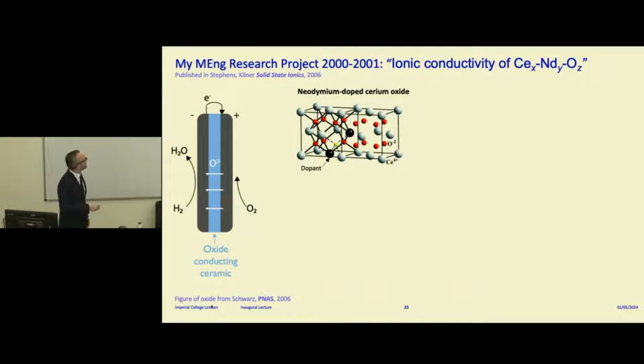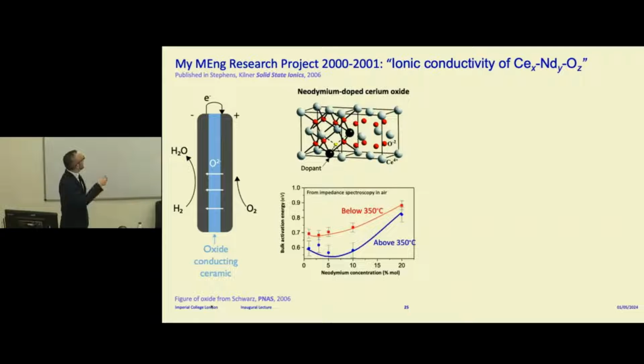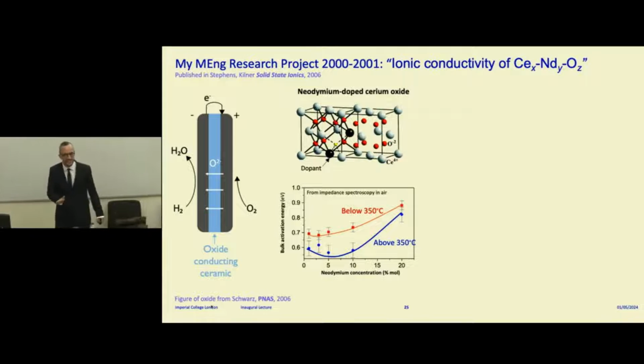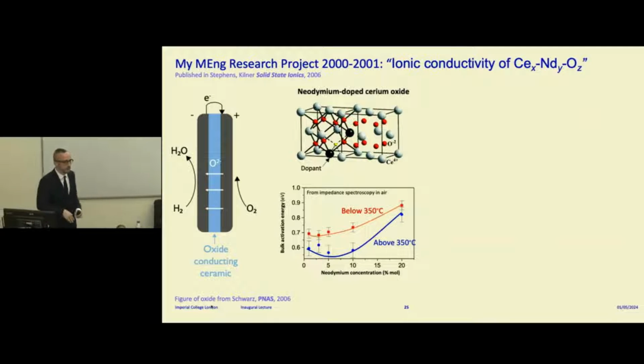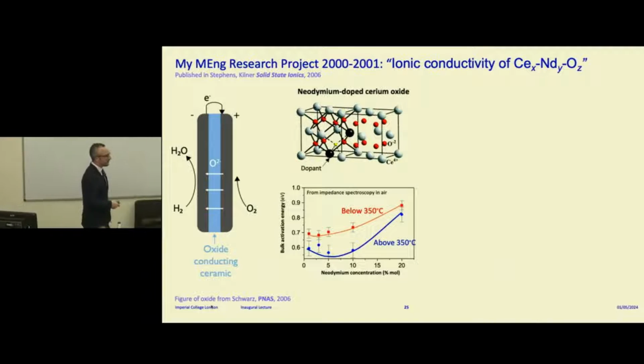Essentially what I did was study how the activation energy for oxygen transport changed as a function of the amount of neodymium, the second metal you put in this oxide. The activation energy is essentially telling you how big the energy barrier is for the oxygen to jump around. So the higher the value, the more difficult it is.